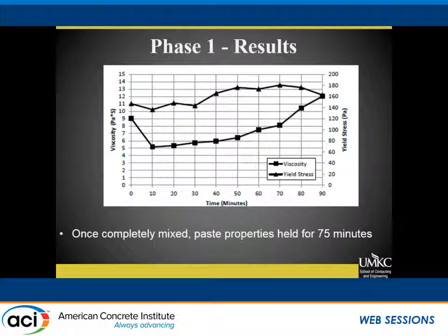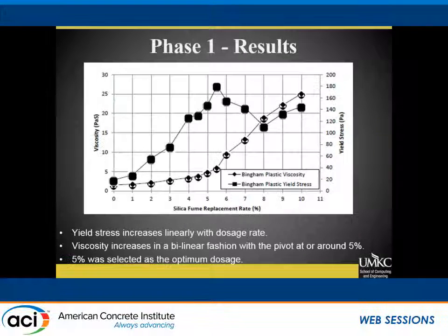So here what we were looking at is just basic mixing performance. We mix it, and we test it initially. The viscosity goes down as we get the water reducer nicely dispersed in the paste, and then it stiffens over time. And so we say once this was completely mixed, our paste had roughly 75 minutes of hold time if we kept mixing it, so we knew at least we didn't have a pervious paste that had issues. So that's the first thing we did.